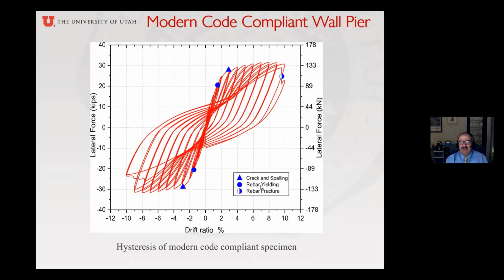So you can see here some of the original things that happen. A 2% drift, which is roughly 2 inches, the rebar started yielding. At about 3%, we see that the concrete started cracking and spalling in this area that I showed you down here in the early days. And then at 10%, actually, we had a rebar fracture. We had a couple of bars that fractured on both sides of the wall. So you can see that, yes, this is much better performance than the as-built. And we kind of knew it, but we needed this point as a point of reference to see, well, how good is your retrofit? How good are you approaching this one?